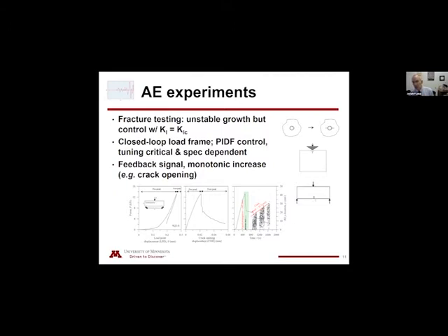If we measure the crack opening on the bottom fiber of the beam, as the crack initiates, crack growth is quite rapid in this portion of the beam, because essentially we're going from a crack with this smooth boundary specimen that's on the order of 1 millimeter or 2 for this particular material to something on the order of 10 millimeters in length. So the propagation of this fracture is rapid as compared to the propagation in this softer type of response that we're observing, where control is much easier.